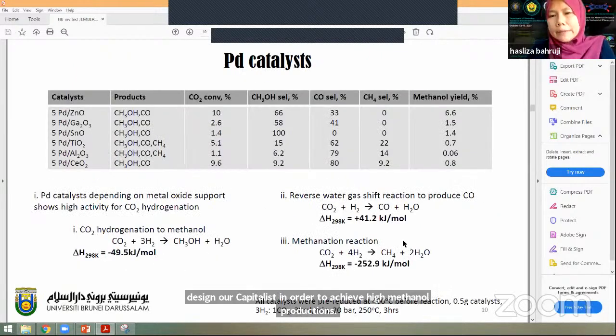So we start with a palladium catalyst. Why are we really interested in palladium? Because palladium has a unique d-band structure that allows us to modify it, convert it into an alloy, or keep it as palladium metal, which has a good ability to dissociate hydrogen for hydrogenation reactions. We have done many works on palladium before, and when we started to work on this CO2 hydrogenation reaction, we tried putting palladium on different types of metal oxides. In this case, we used zinc oxide, gallium oxide, tin oxide, titania, alumina, and ceria.